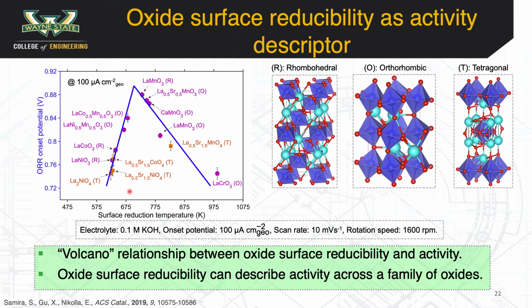Since n equal to 1 and n equal to infinity type perovskites can be described using oxide surface reducibility in terms of surface reduction temperature, this suggests that oxides in between, with n equal to 2 all the way through n equal to infinity, can also be described using such a descriptor.